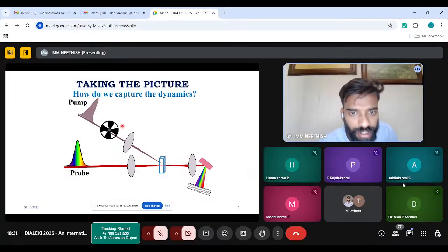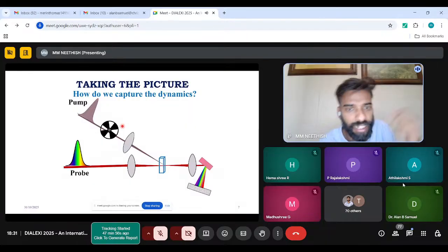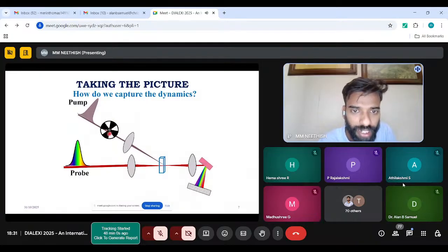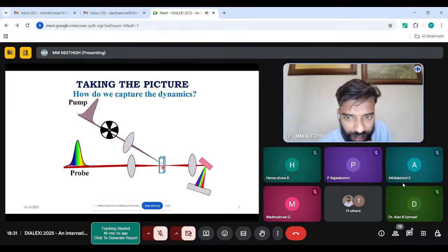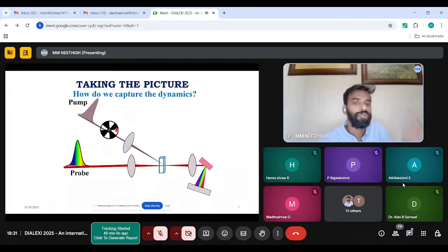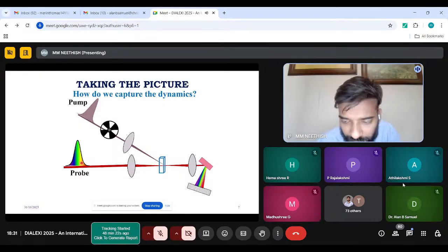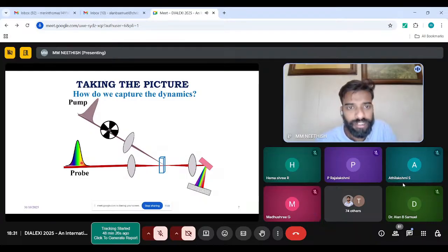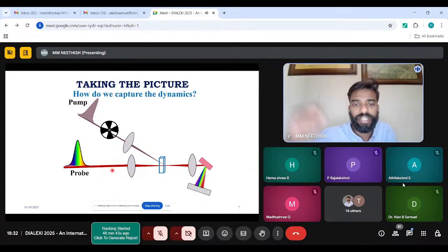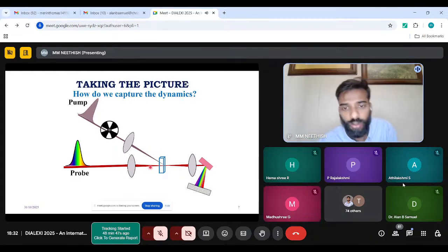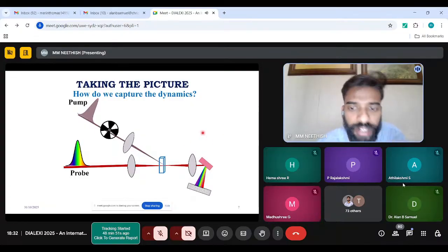The rotating wheel inside here gives the possibility to explore what happened when the pump is on and when the pump is off, because you have two areas in this rotating wheel. One is open and one is closed. The closed region gives the option to understand what is happening when the pump is not there, which you can take as a background and subtract from the other result, which is the result of when the pump is on. You do this for a moment, then you move the probe in time by some femtoseconds, and you see what happens after this many femtoseconds after the pump has hit the sample. Then you move the probe again and you understand what happens after 30 femtoseconds. Then you move again, and you understand at 40 femtoseconds. In this way, you do it multiple times and you understand the evolution happening at different time positions. You collect this information and you can reach a conclusion.